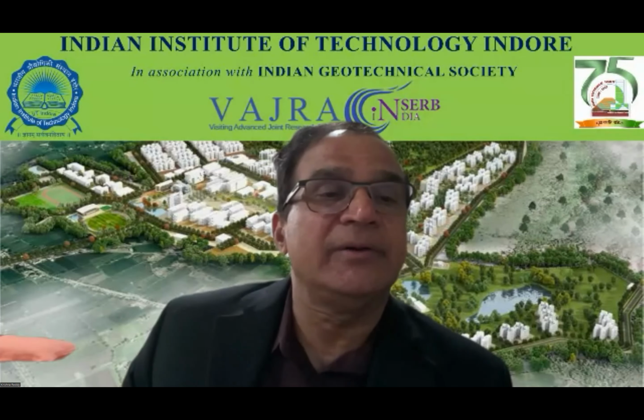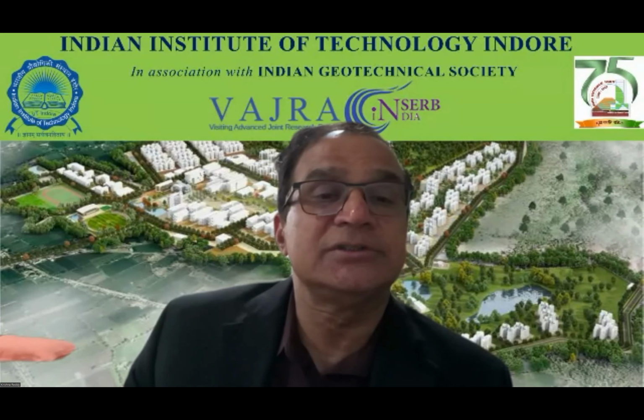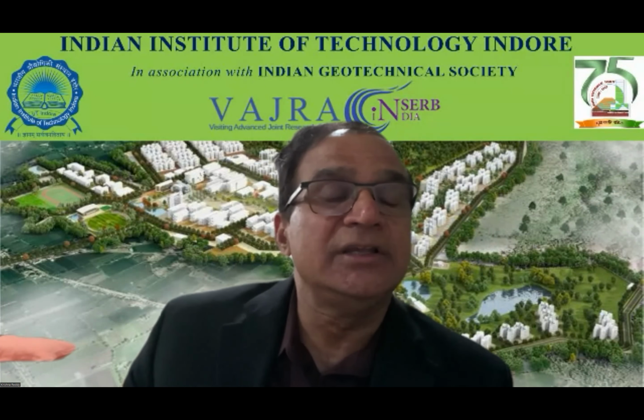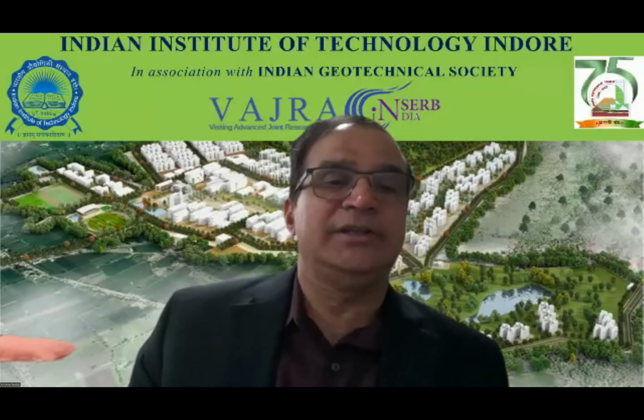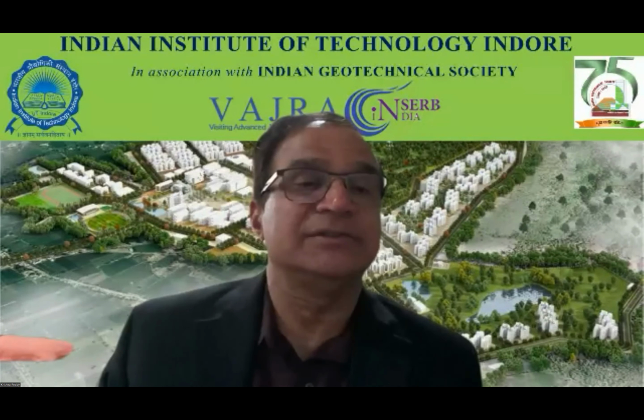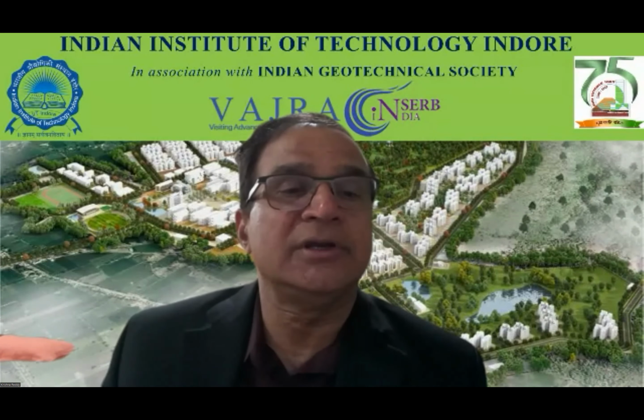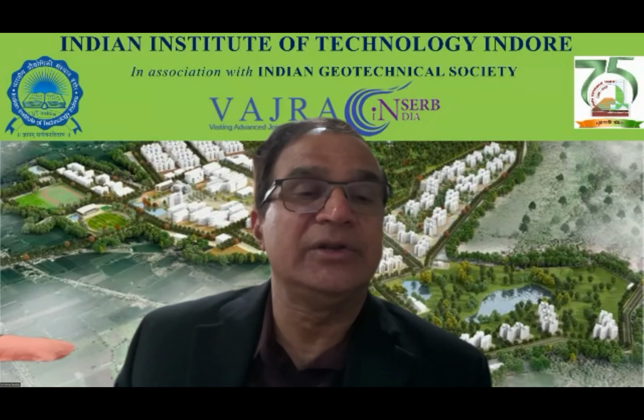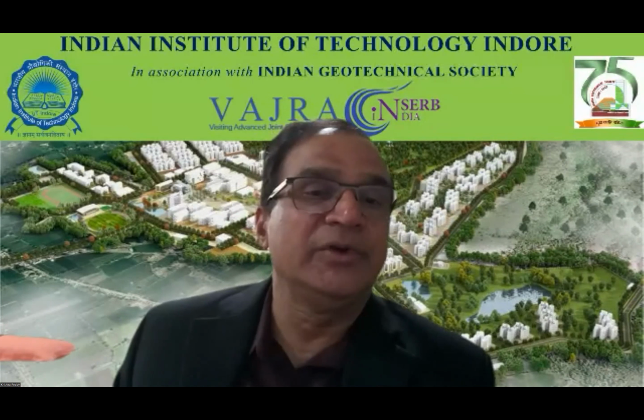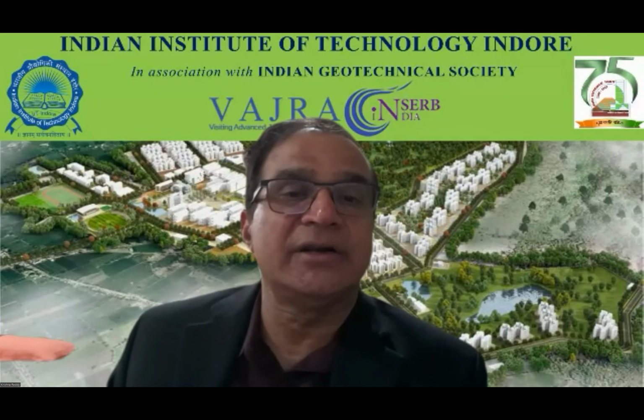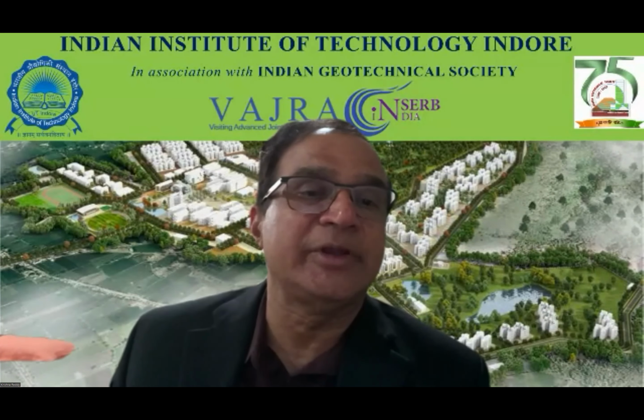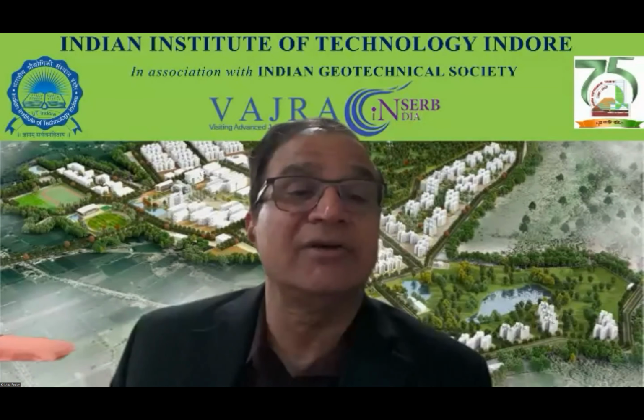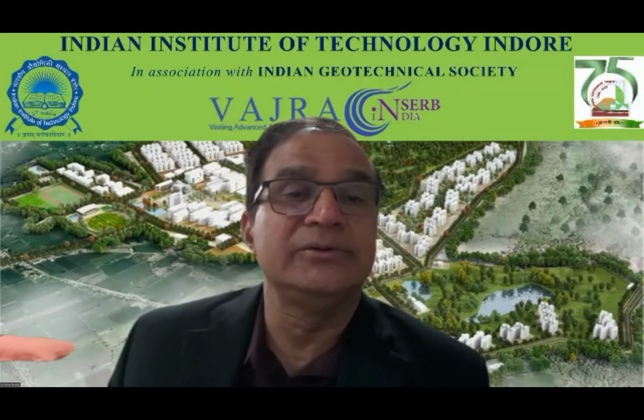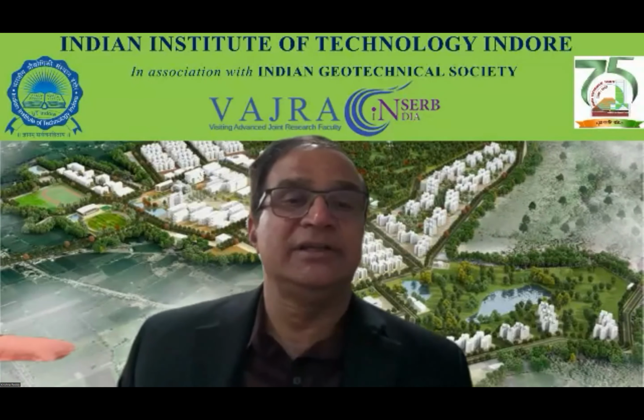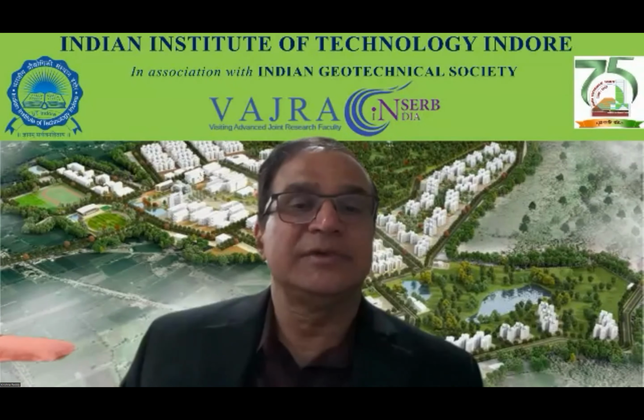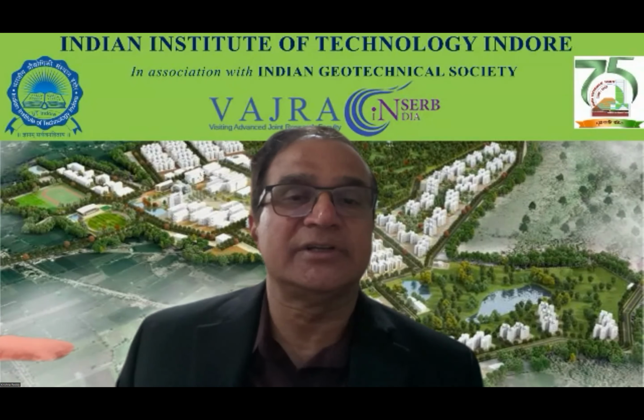The question is, can this technology be used in industry before disposing the waste contaminant, in the form of a screen or filter unit? Yes, you actually can. If you are interested, you can use scrap iron itself. That can remove a lot of contamination, so you don't have to use it in nanoscale form. The nanoscale form is suitable so that we can inject it into the ground. But we also did a lot of experiments using scrap iron as filter material, and it's very good. It can take out chromium and other things too. So to answer your question, if you have waste or wastewater, you can use scrap iron that you can get from any iron stockyard. You're using a waste material that costs nothing for treatment.